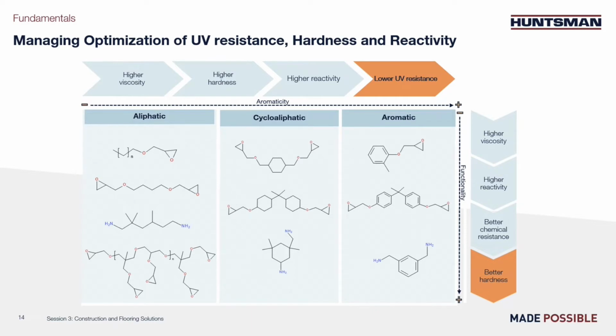To go around that, we can play with the functionality of the components, meaning how many reactive sites per molecule. In the three columns, from top to down, there is an increase in this functionality. It leads to higher viscosity and reactivity. It also leads to better hardness and better chemical resistance because the resulting cured material has higher cross-linking density. So in principle, it is possible to get a fully aliphatic or cycloaliphatic system, but you need to take care that you get a good combination, curing well, and the resulting material hard enough. We will propose combinations which fulfill those needs after.